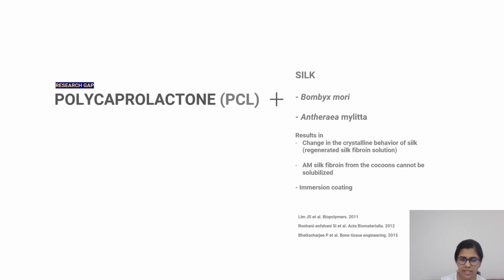In addition to this, there is no single protocol where they can form regenerated silk fibroin solution from both the silk variants. For Bombyx mori, a chemical treatment with lithium bromide is done. For Antheraea mylitta, it being a wild variant, it cannot be solubilized. So the direct silk is taken from the gland of the silkworm, which itself requires a lot of expertise.